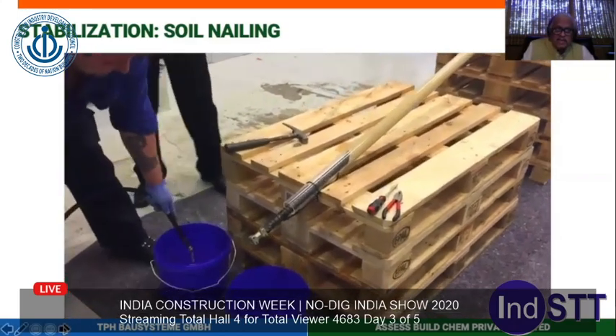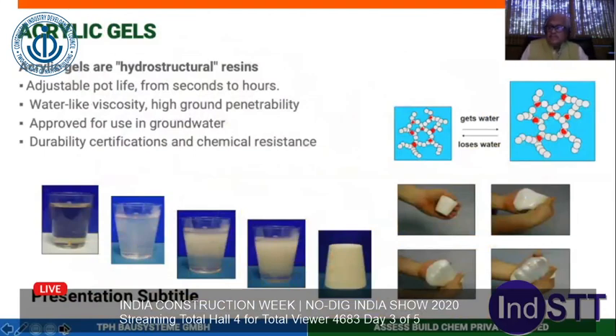And these are the resins that you have to consider as new generation resins, and a still more versatile material is the acrylic gels. These acrylic gels are fantastic as far as sealing is concerned. They have got adjustable pot life. You can adjust the pot life from 9 to 10 seconds up to 30 minutes, depending on the flow of water, depending upon the penetrability. They have the lowest viscosity, they can penetrate to the finest possible pores, as good as water. Wherever water can reach, they can reach.